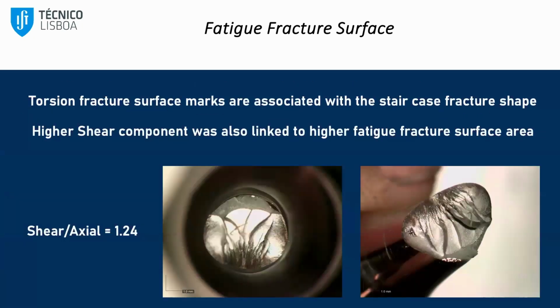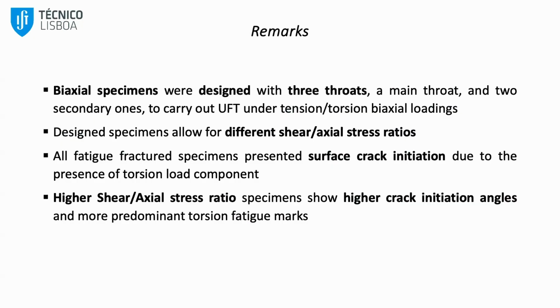Okay, so this is the highest stress ratio that we have considered, 1.24. And as you can see here, the stair case fracture shape is most prominent and evident. So this is linked to the higher shear component that was applied in these tests. Okay, so these are the final remarks.